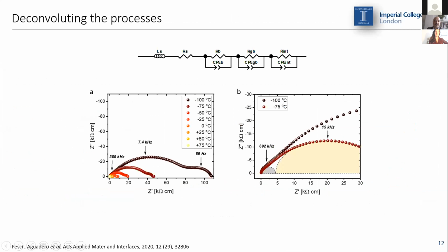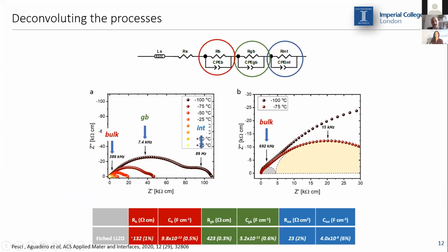if we actually run electrochemical impedance at low temperature, such as minus 100 degrees, minus 75, we can see that at high frequency, we've got the appearance of a feature in the impedance spectrum. So we can then see the presence of three distinct features. We can then fit our data using a combination of three RC-CPE circuits. One will describe the interfacial processes, one will describe the grain boundaries, and the third one will describe the bulk processes.